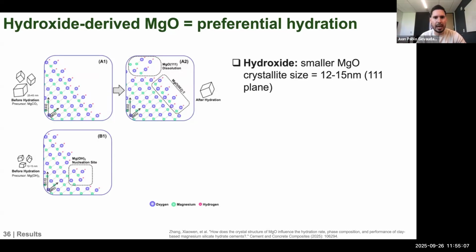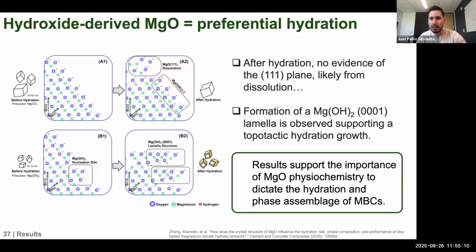That is really important because after hydration in the cement, we see that there is likely this formation of a lamella structure because we see evidence of the 0001 plane for magnesium hydroxide. Now, the interesting thing here is that the 111 plane of magnesia and the 0001 plane of brucite are topotactically related. So it's almost like you're unzipping a zipper when you're hydrating that magnesia to brucite.